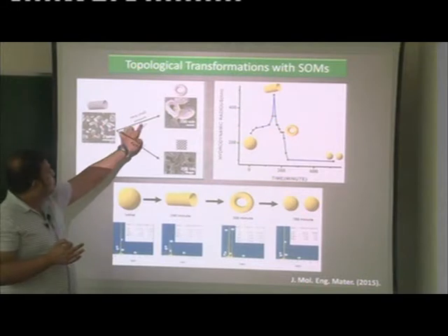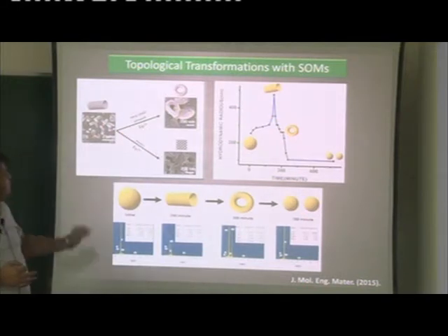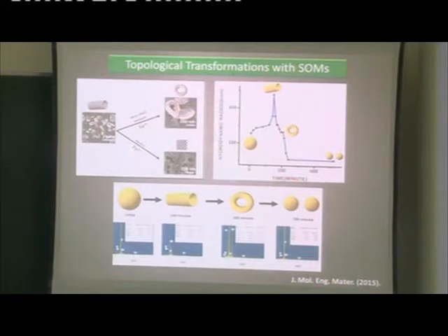and then we were able to stitch the rods by adding small amounts of iron 3, which gives rise to these donut-like structures, and we monitored them in detail with EDX and with microscopy, and we were able to show that you have a competition of length scales that leads to the formation of different types of structures. Why did we do that? We are interested in doing selective catalysis with different shapes that we have got so far.